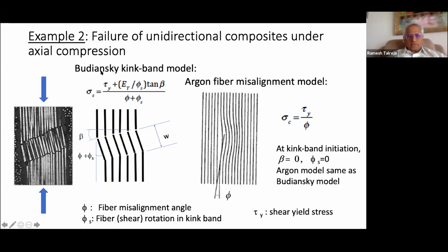So in the Budiansky model, which is classical for this, the geometry constructed has parameters of initial fiber misalignment phi, the rotation of the fibers within the kink band, phi sub s, and this is the bandwidth, and beta is the tilting angle of the kink band. Okay, using all that with a refined analysis, Budiansky produced this relationship that says what is the stress that you apply at which you have rotation of the fibers. So it's an academic result, very exciting and all that. But you ask yourself, if you are designing and you don't have a kink band to look at, you don't want to have a kink band, how do you get this sort of information in your design? So you had to do some estimates.